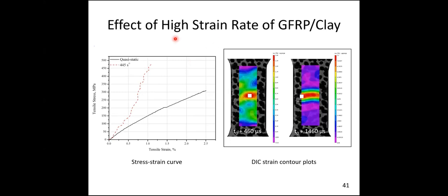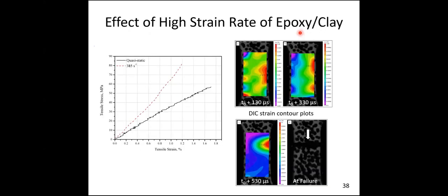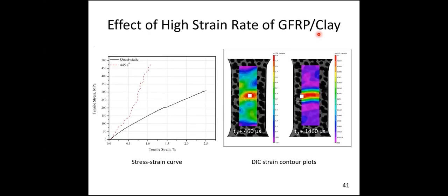Again, this is another figure, the effect of strain rate on glass fiber reinforced polymer clay. The previous slide shows the effect of strain rate on epoxy clay, where there is only clay and matrix, but here we have fiber, matrix, and clay. Again, at quasi-static, the strength is around 300 megapascal, whereas when I do the testing at high strain rate, it is increased to 450 megapascal. From this, we understand that when I do the testing at low speed, I get some properties. Similarly, when I do the testing at high speed, the properties will be different. So this is what I wanted to convey to this forum. This is the figure just before the failure, and you can see the strain localization.